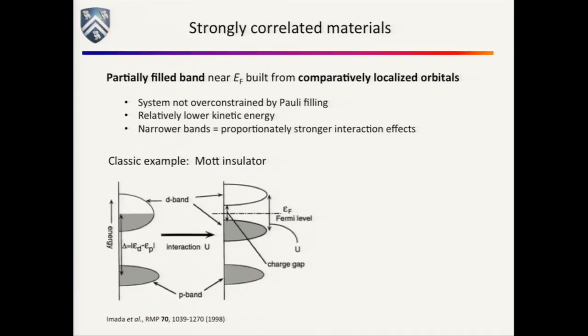The most famous example of this is something called the Mott insulator. So I can have a system where here's a filled band, here's a partially filled band, and imagine this could be a copper oxide plane in the parent compound of the high-temperature superconductors. It's a little more complicated than that, but it could also be something like some of the d bands associated with iron in something like Fe3O4, right? If you do simple electron counting with Fe3O4, you come to the conclusion that it should be a metal, because your Fermi level should be in the middle of a partially filled band. In practice, the material is not a metal.